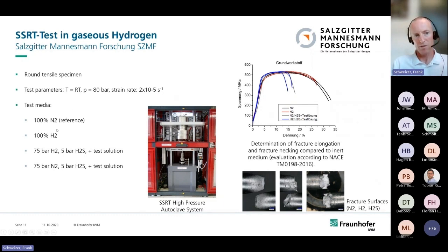In the H2S project, Salzgitter used an inert gas, hydrogen, and a mixture of hydrogen and H2S. And you see the results of a tensile test on the right side. So you tension the sample and measure the stresses, and you see the black line. This is inert gas. Red line is hydrogen, the gray line is N2 and H2S, and the blue line is hydrogen and H2S. And you see that the material is not able to deform so much the more hydrogen comes inside. And you also see this on the fracture surfaces. On the left, this is inert gas, and you see changes with hydrogen, and you see large changes with H2S.